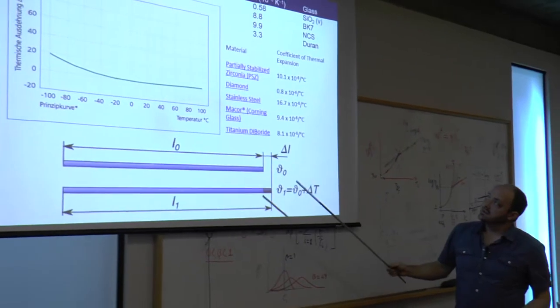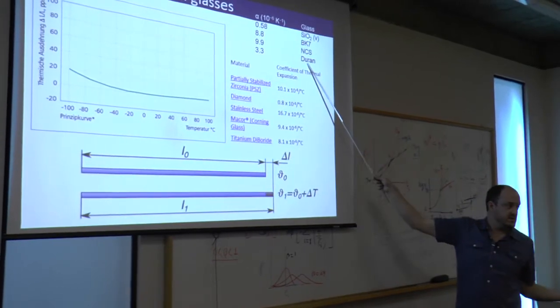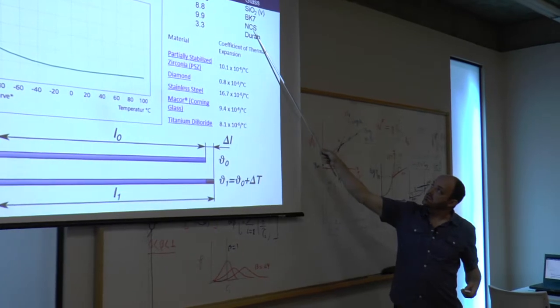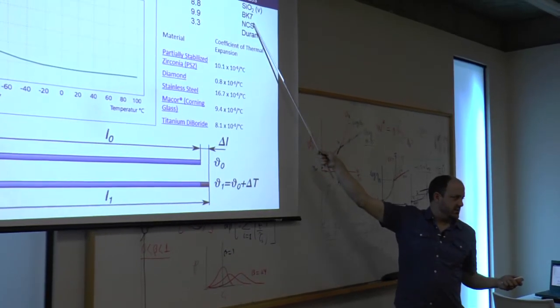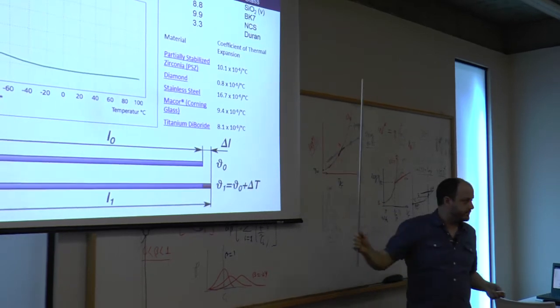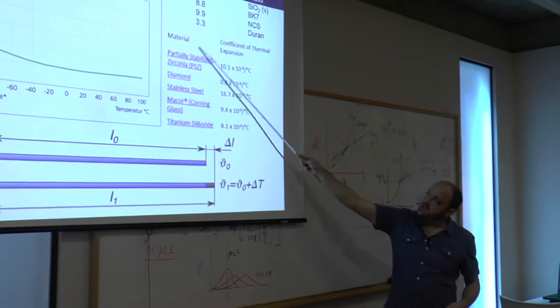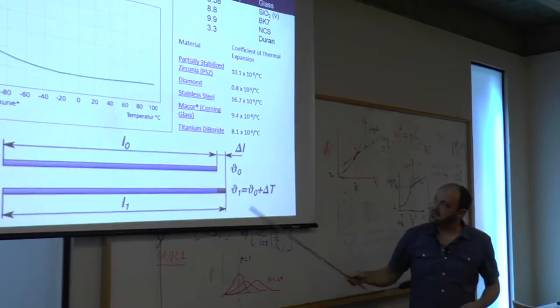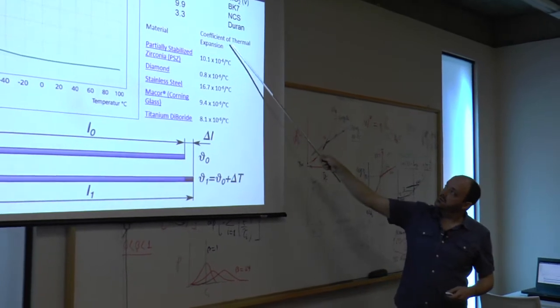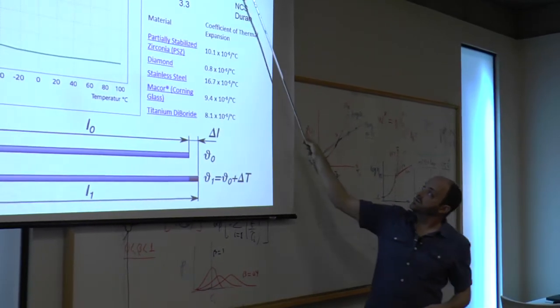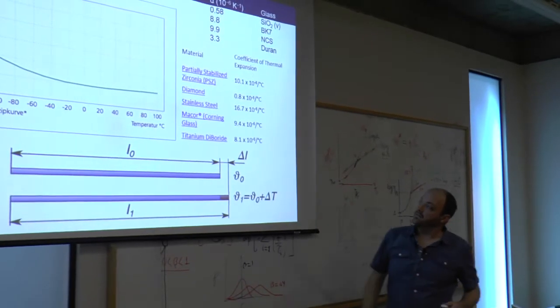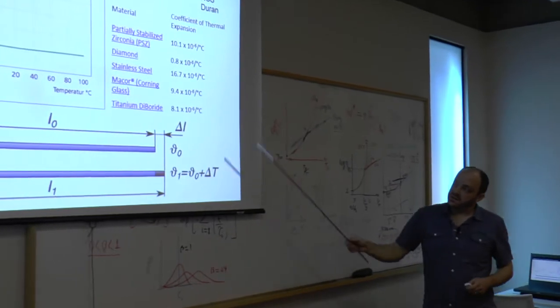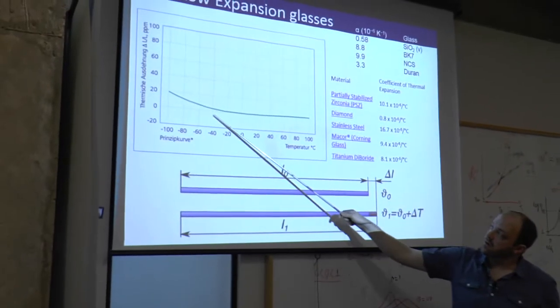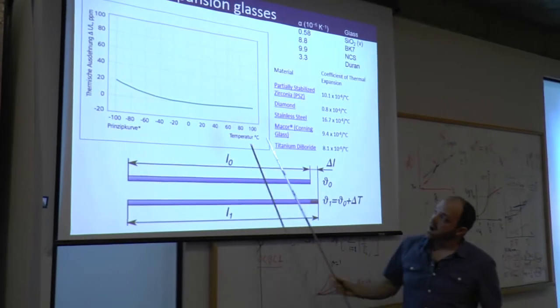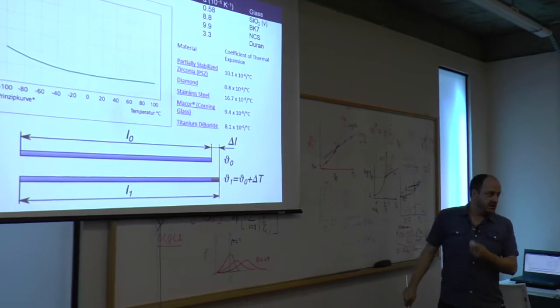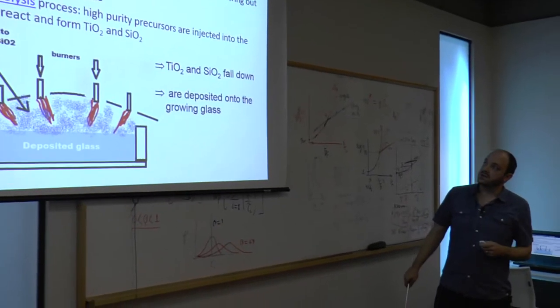If you look at most glasses, and there's some examples above here, the Duran type glass, you've seen this a couple times from Doris's work. This is sodium calcium silicate. What's the BK7? I don't remember. Optical borosilicate. Yeah, and you can see some other materials here, Corning glass, Macor, titanium diboride. They have a thermal expansion coefficient around 10. And for this, vitreous silica is around 0.5. So this is an ideal scenario where we have a very small thermal expansion over this quite wide temperature range. So very good for making these telescopic measurements from looking at things in outer space.